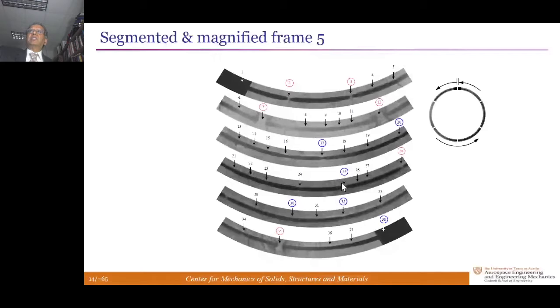If you take one of those images of the ring and expand it out, enlarge it to see more detail, you could see there are about 40 necks that form in this one particular experiment. Of those, the ones marked in red are broken at this frame. The ones marked in blue will break in the next frame. We know that because we have the next frame. And the ones that are marked without any symbols around them did not break, did not even proceed to full necking. They necked to some extent, but then got unloaded because the driving force was interrupted when the specimen broke. There was no more stress in the specimen.